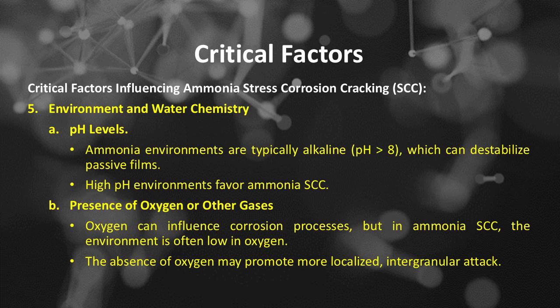Critical factors. Number 5 is environment and water chemistry, includes, number A, pH levels. Ammonia environments are typically alkaline, pH greater than 8, which can destabilize passive films. High pH environments favor ammonia SCC.